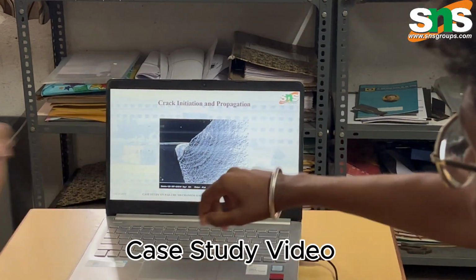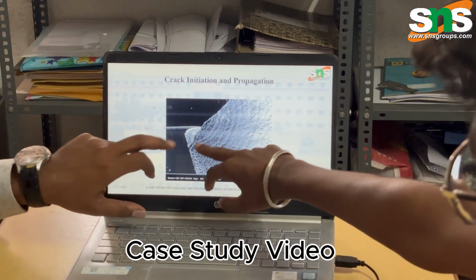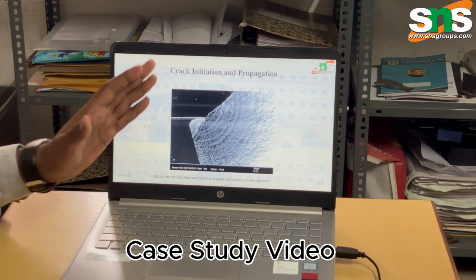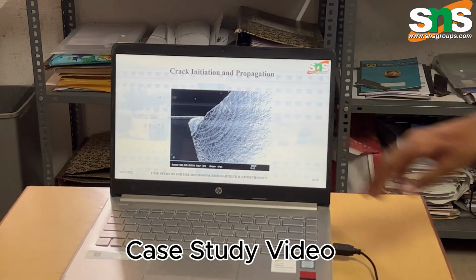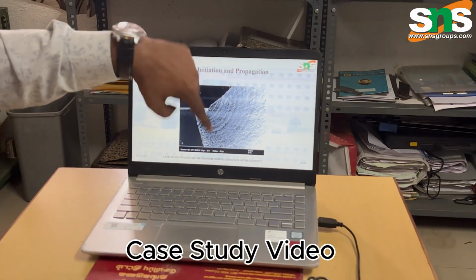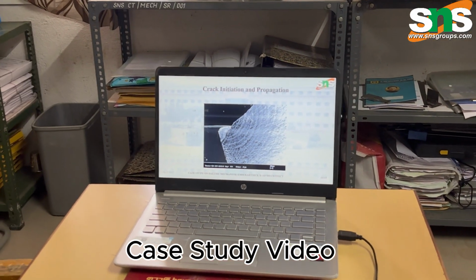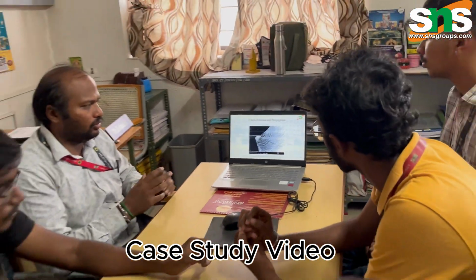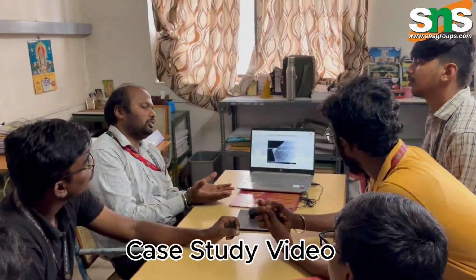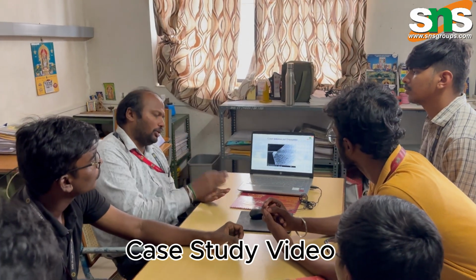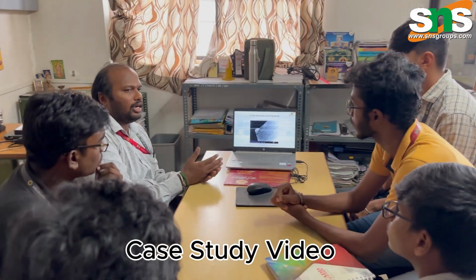The start area is here, at the tip, and it moves towards the outside. These marks are nothing but fatigue striation marks. With these fatigue striation marks, you can easily find from the examination that this particular failure occurs majorly due to fatigue, and in addition pitting and spalling have taken place.